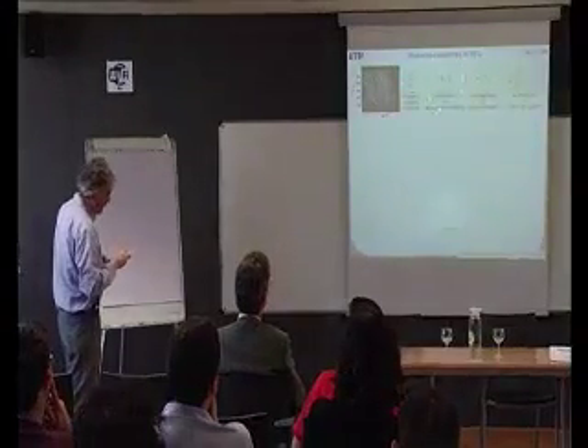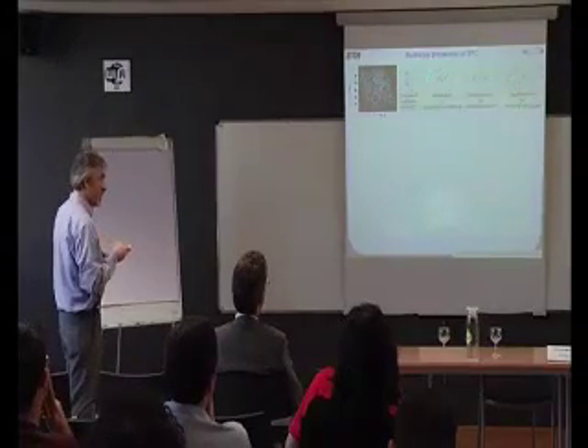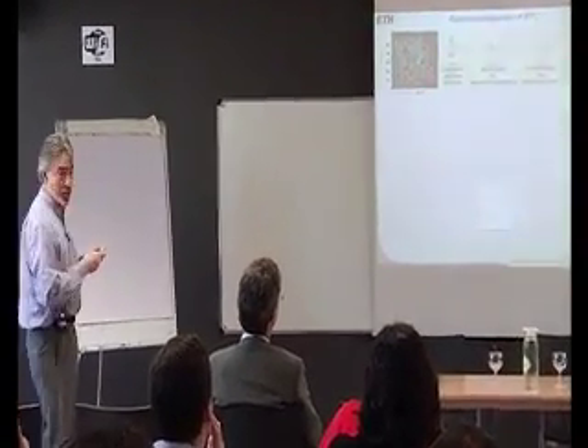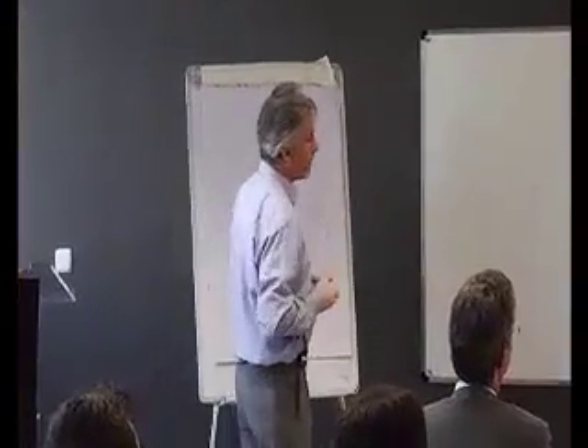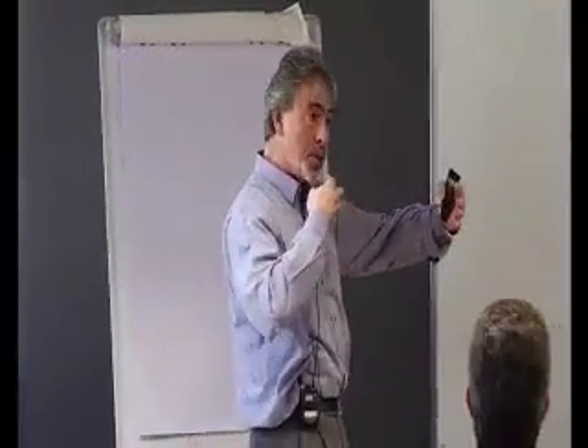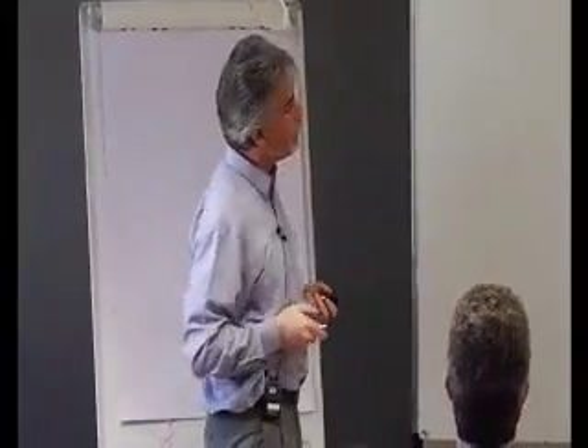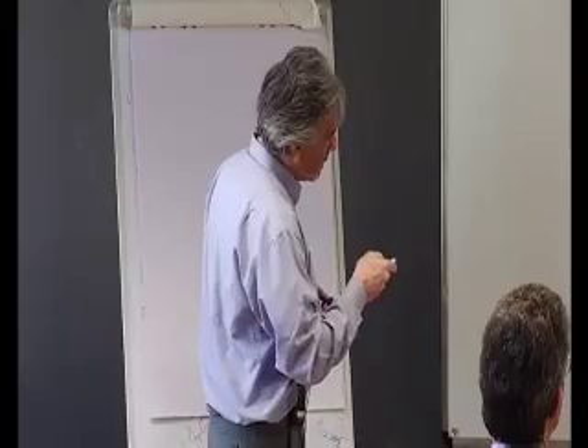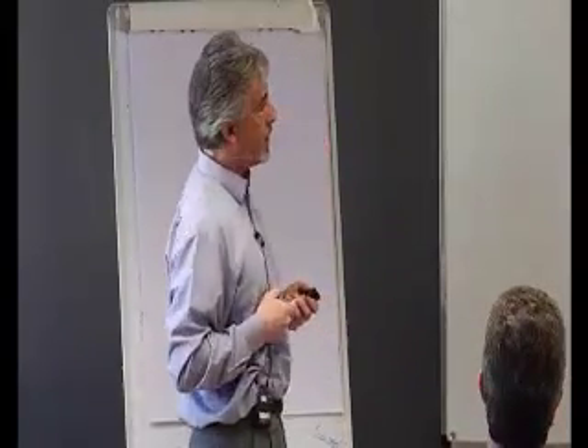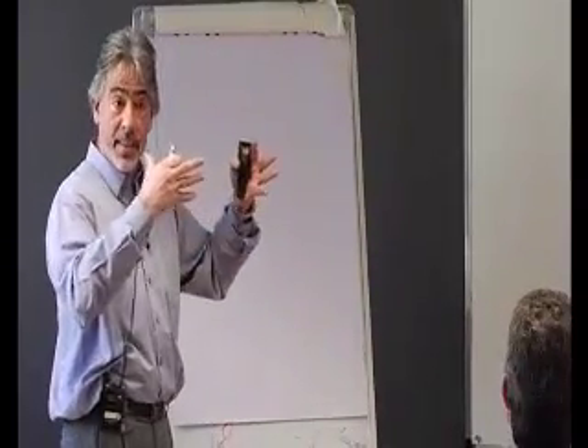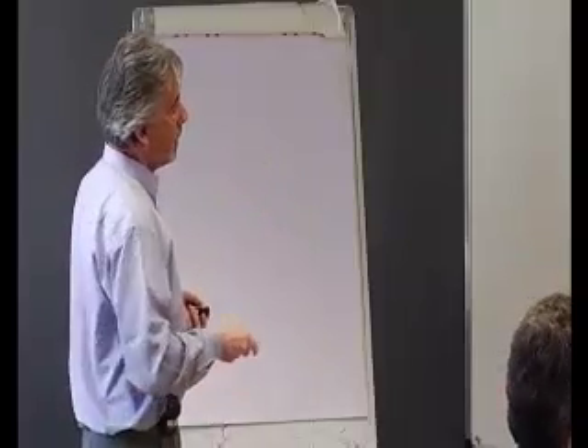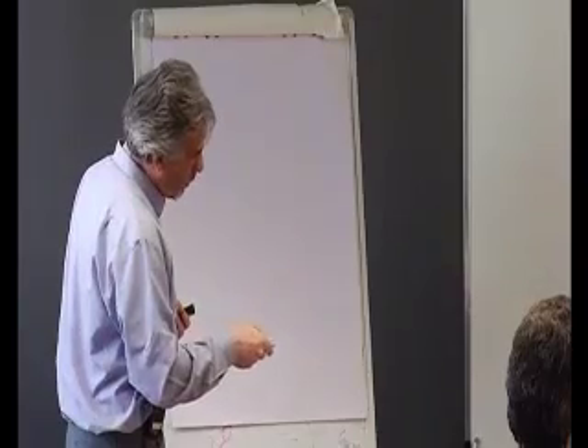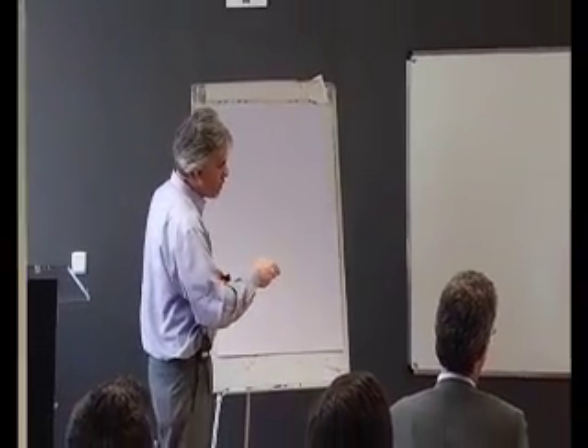So the way to do it is we solve the equation of radiative transfer that is giving three contributions. A negative contribution, this is radiation being attenuated by absorption and scattering, and then 2 positive contributions by internal emission because the RPC is hot, and by incoming scattering. Solving this equation tells you how radiation travels as it penetrates into the RPC. We need to know the properties of the material, specifically the extinction coefficient and the scattering phase function, which we can calculate because we have the 3D representation. We can do ray tracing at the pore level and plot the probability of attenuation as a function of the path, here normalized to the pore size. And the slope of the curve is nothing else than the extinction coefficient.